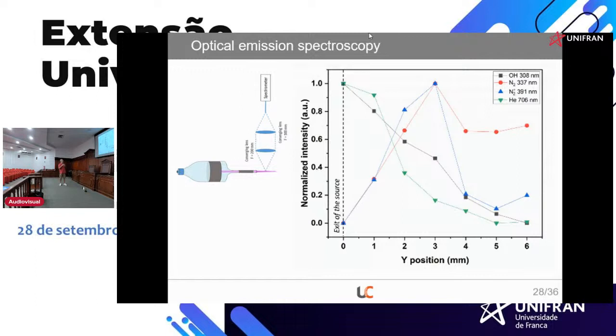So we see here, for example, in black, it's OH. There is a decrease of the OH when you go away from the nozzle. But there is an increase of some ions and some nitrogen. So depending on the distance at which you place your surface, you will not have the same species.